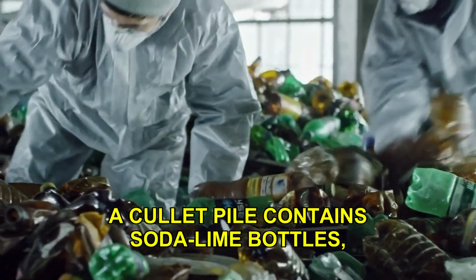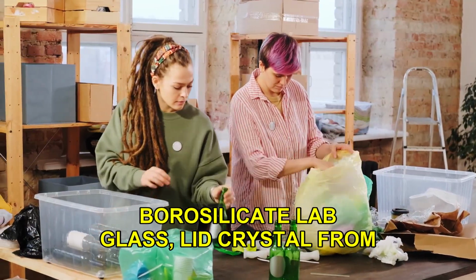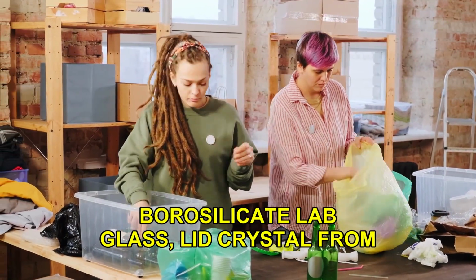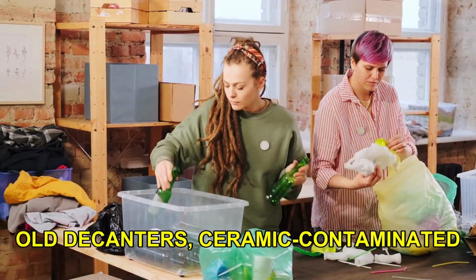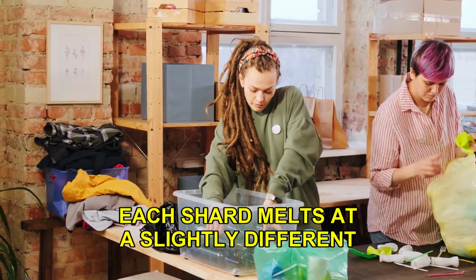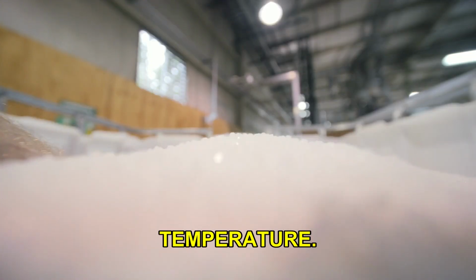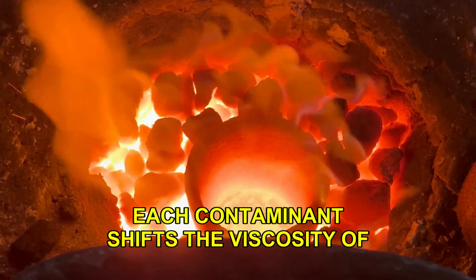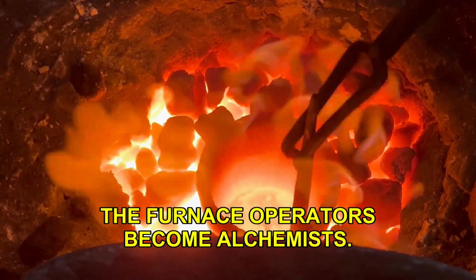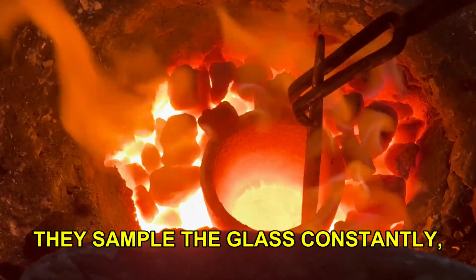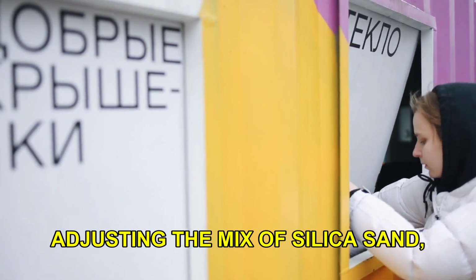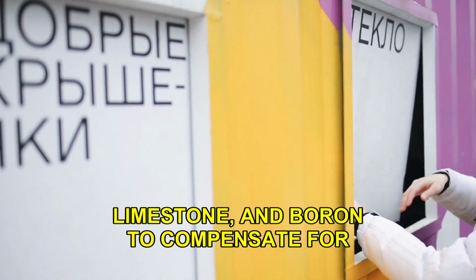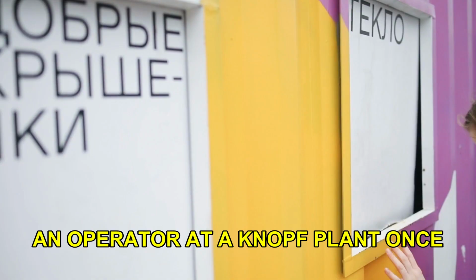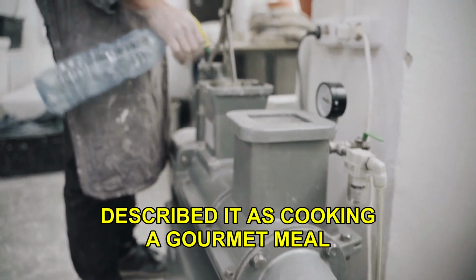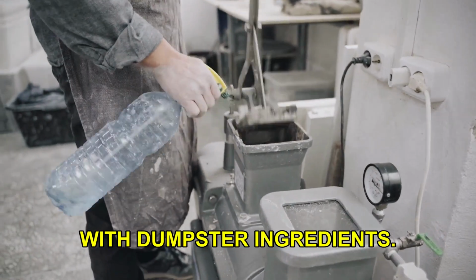A cullet pile contains soda-lime bottles, borosilicate lab glass, lead crystal from old decanters, ceramic-contaminated curbside pickups. Each shard melts at a slightly different temperature. Each contaminant shifts the viscosity of the molten river. The furnace operators become alchemists. They sample the glass constantly, adjusting the mix of silica sand, limestone, and boron to compensate for whatever chaos the cullet brings. An operator at a Knauf plant once described it as cooking a gourmet meal with dumpster ingredients.